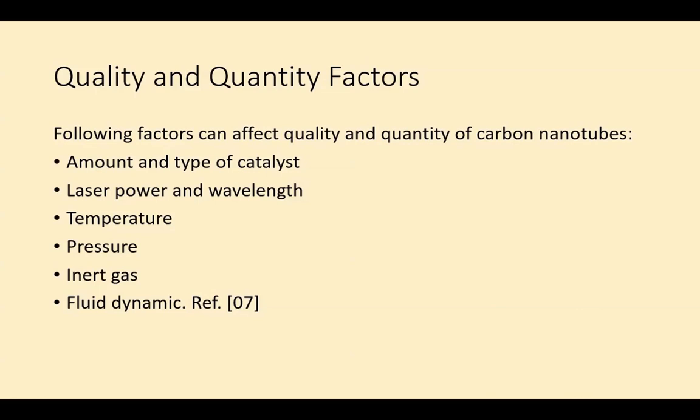in large bundles. The type of produced carbon nanotubes is highly affected by the applied pressure and temperature of the carrier inert gas. Increasing the temperature decreases the cooling rate, and then fewer carbon nanotubes are produced. Also, the inert gas matters.